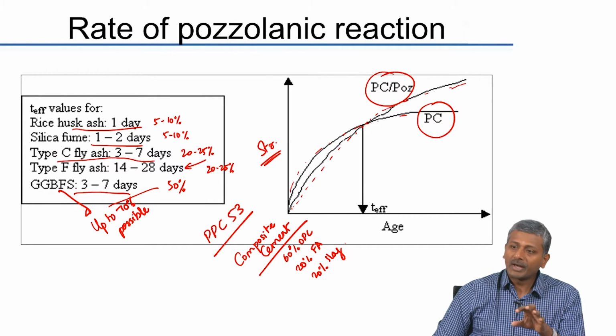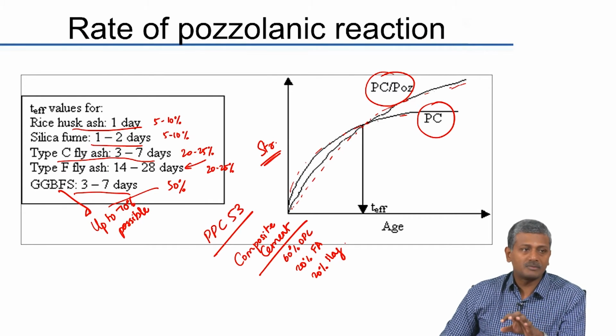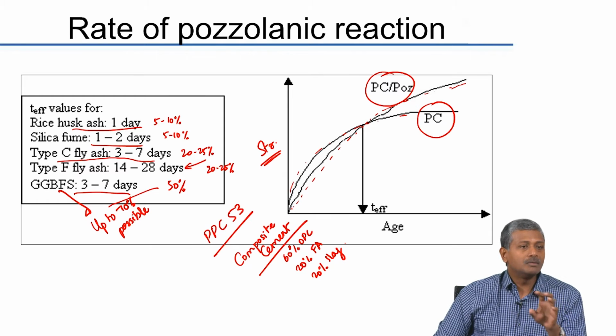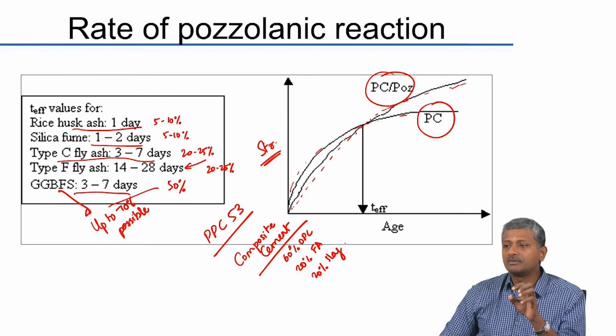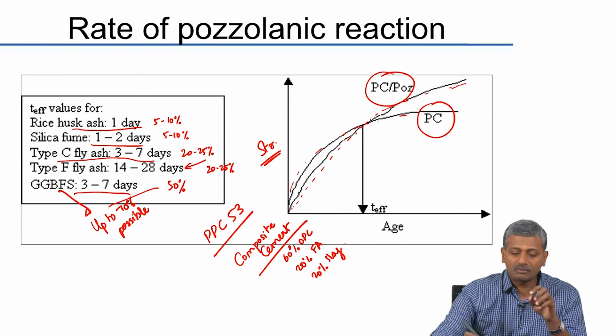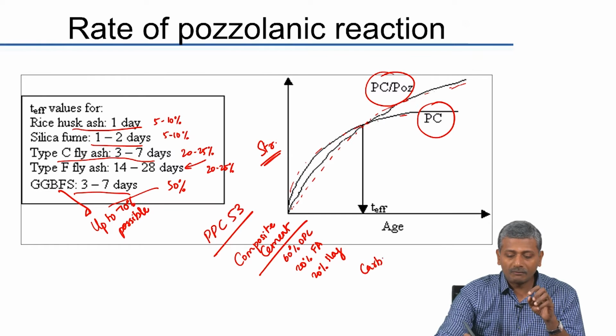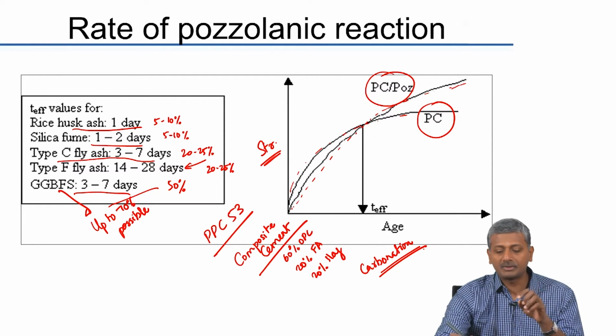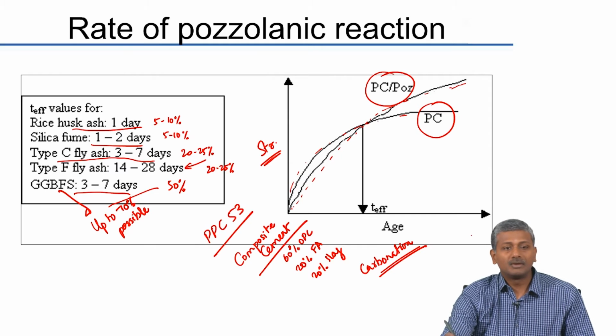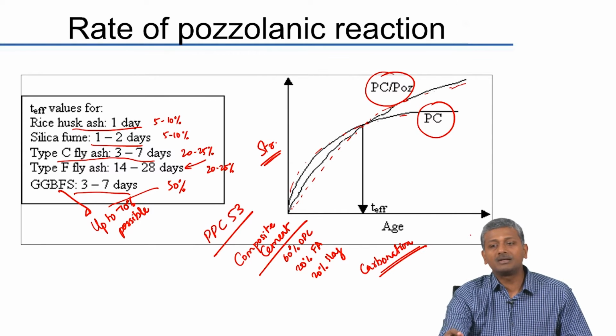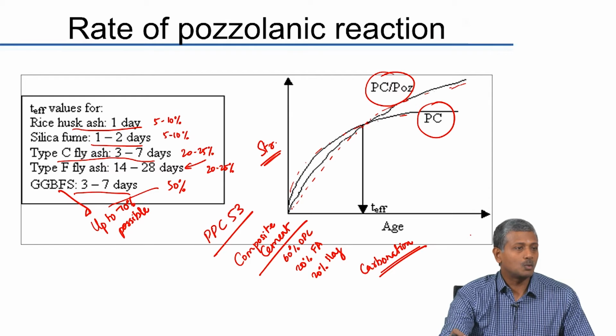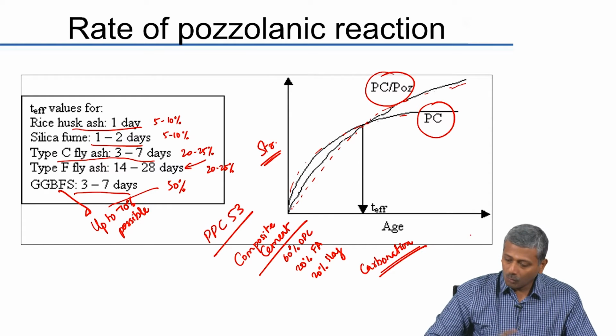Now, while in all those characteristics this composite cement is very good, the one problem which can occur with composite cements is a higher rate of carbonation. Now, I have not talked about this earlier, but we will talk about this in more detail in the durability chapter, that the carbonation rates when you replace cement in large quantity by mineral admixtures can get to be quite high. Okay. And what is the reason for that?